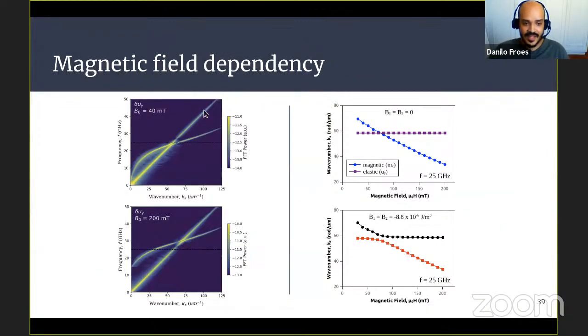By changing the magnetic field intensity, the magnetic curve changes its position, as you can see here, 40 millitesla, and here 200 millitesla. The magnetic curve changes, but the elastic curve doesn't. This causes the crossover region to change its position. What I did was turn off the coupling and measure the magnetic wave number peak as a function of the external field, and the elastic one without coupling. The elastic doesn't change its wave number position because it doesn't care about the magnetic field, but the magnetic one varies. The wave number becomes smaller as the magnetic field gets more intense. And when we turn on the coupling again, we see our anti-crossing again.